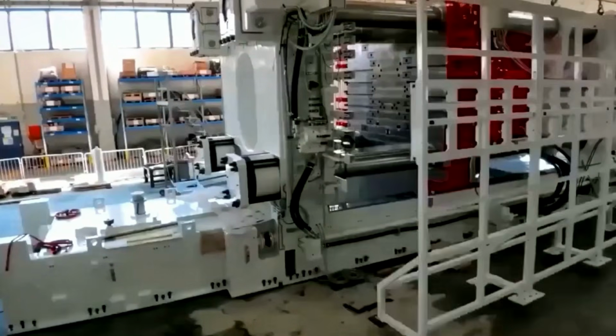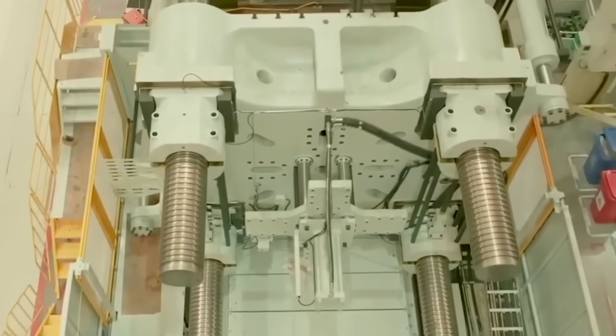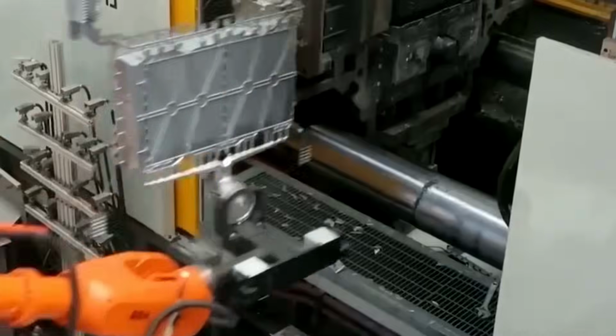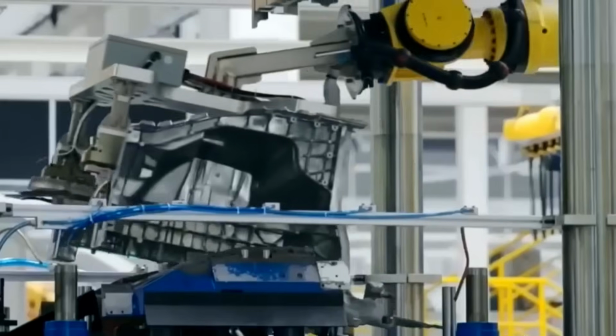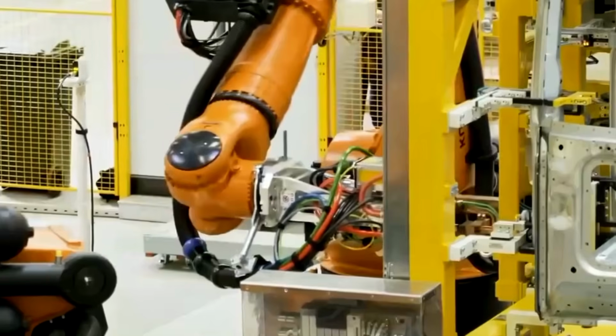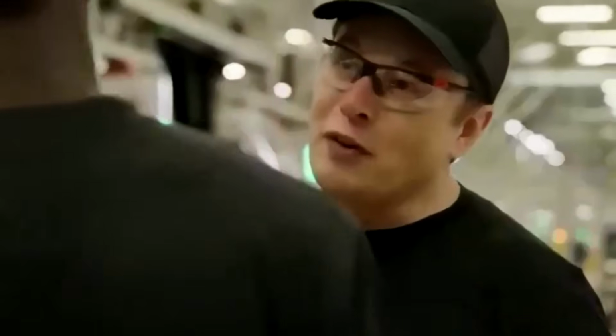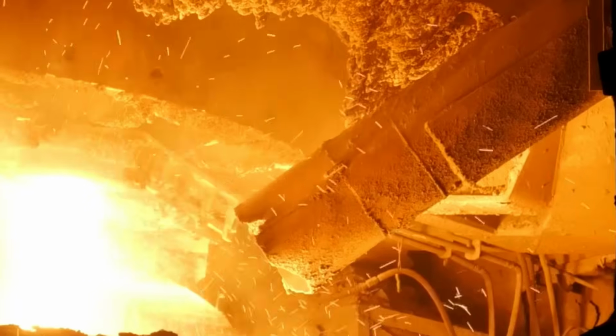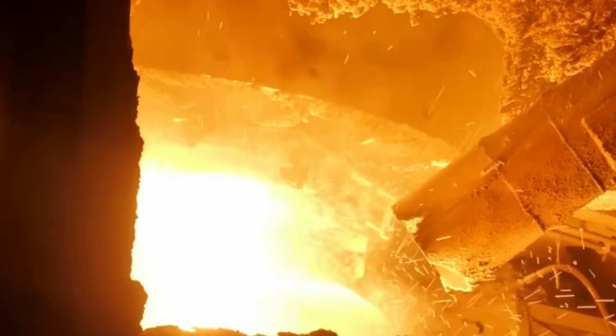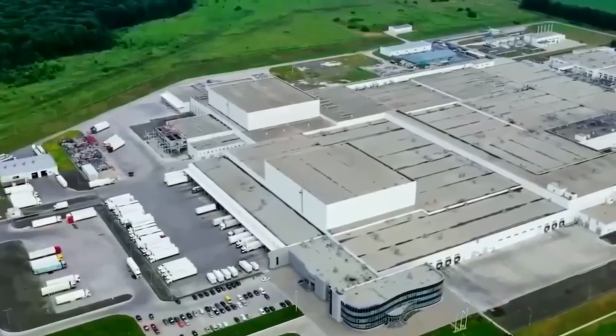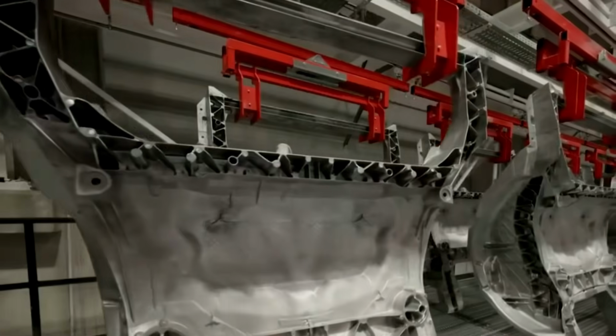This is not simply about speeding up the process. Rapid cooling eliminates a number of casting defects and improves the mechanical properties of the material. The die, meanwhile, cools to approximately 185 degrees, after which a robotic system cleans every surface. The next cycle can begin within just 1 to 2 minutes. Excess aluminum is sent back to the melting furnace. Every finished casting undergoes X-ray inspection to verify its internal structure.